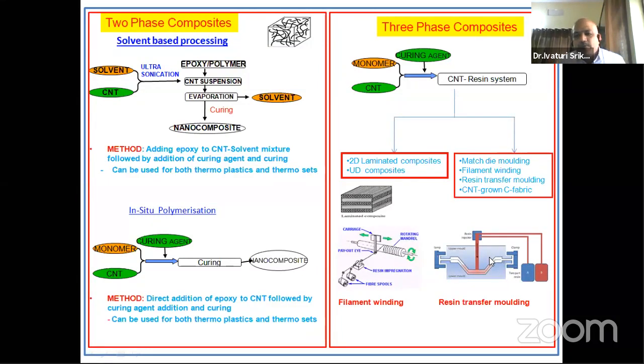The other widely used method, for flat structures like aircraft wings and other things, works like this. You can see here, this is an area where big fabric layers are put, and then the resin is allowed to pass through them. This is called resin transfer molding. You mix your CNTs into the resin system and then apply vacuum at one end so that the resin with the CNTs gets transferred through the fabric system, then you cure it.